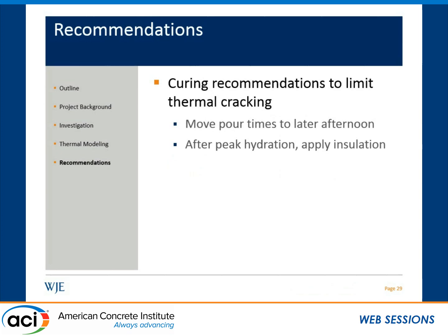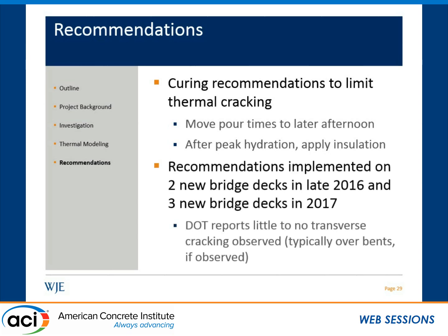The first set were to limit the risk of thermal cracking. The two recommendations we made to them were to move the pour times to later in the afternoon so that the peak concrete temperatures didn't coincide with the coolest temperatures of the day. Instead, the peak concrete temperatures are going to correspond with the peak temperatures the following day. That would limit some of those early age temperature differences that we were seeing. The other recommendation was, after the peak hydration temperature was reached, to apply insulation with curing blankets. And Montana actually implemented these